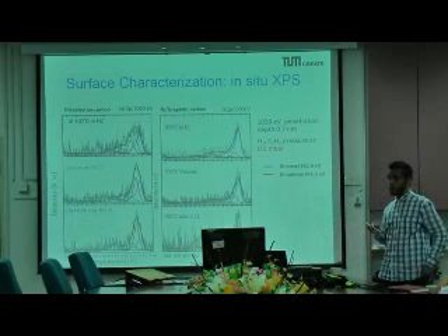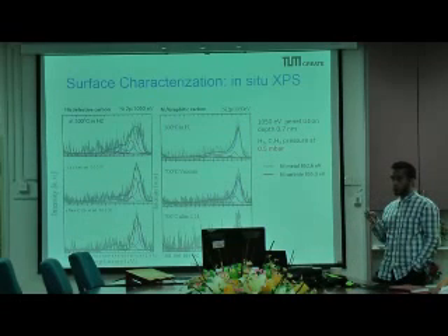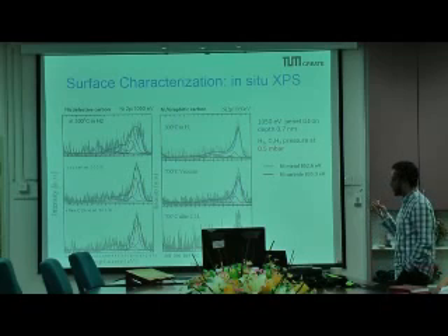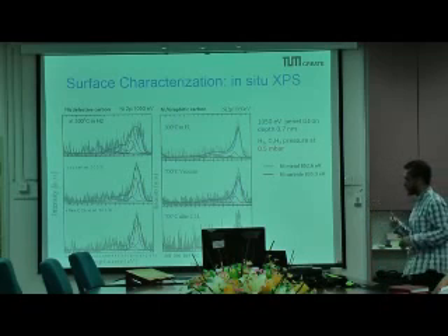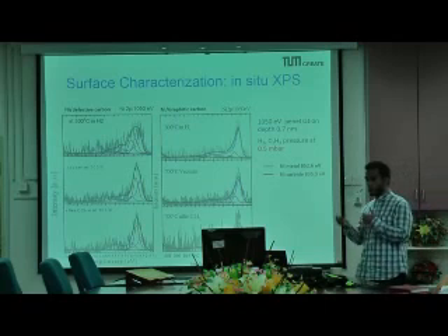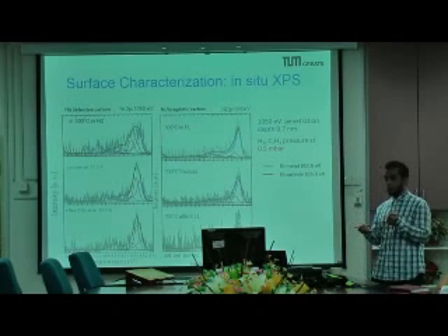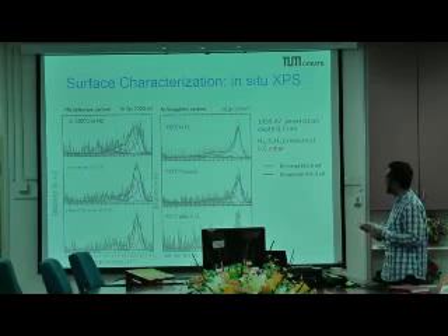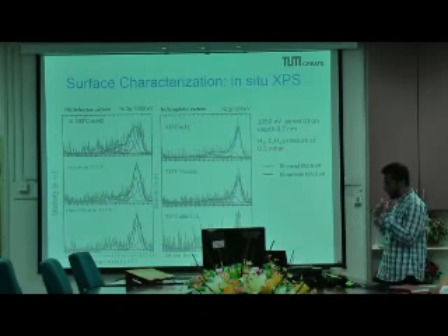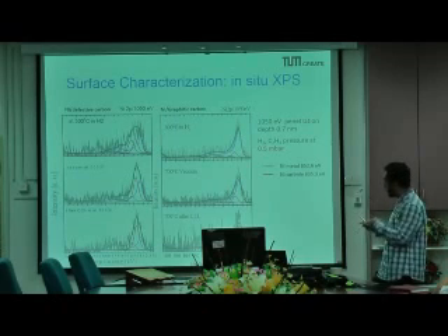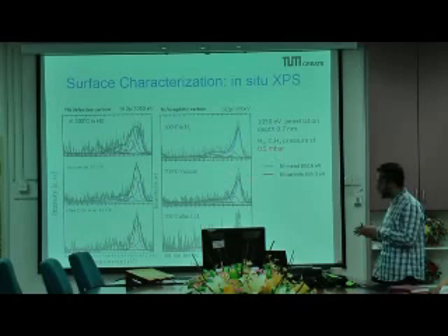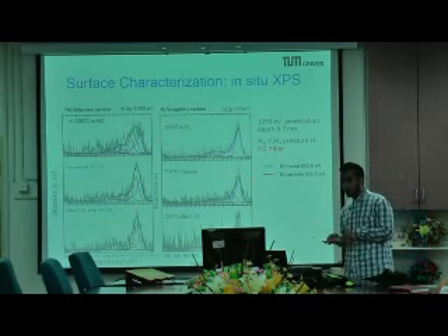So the next investigation that we want to do is to see whether on the surface of the nanoparticle there is also a change in the carbon amount. So what we did here, we did in situ XPS, measuring XPS under slightly elevated pressure conditions, in this case 0.5 millibar of either hydrogen and ethylene.